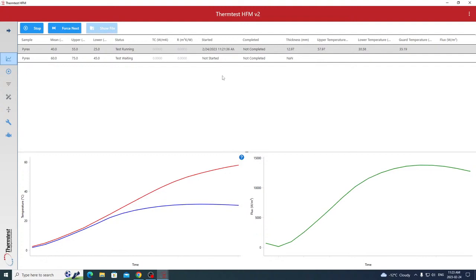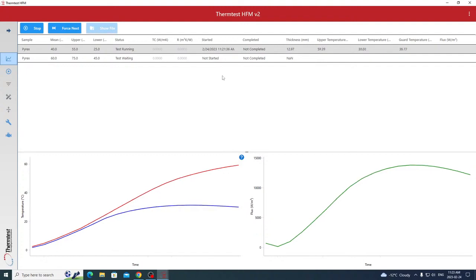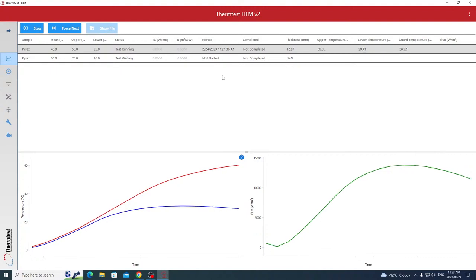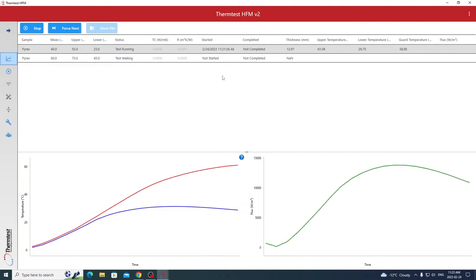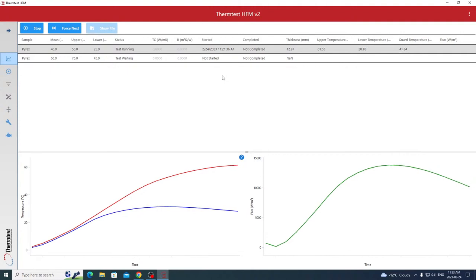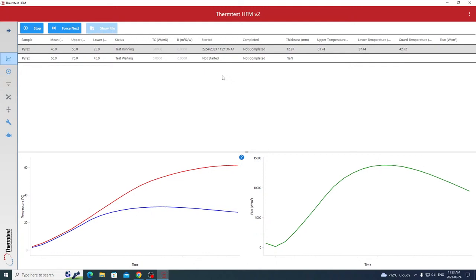Doesn't matter who the maker of the transient method is. Any heat you introduce into the sample, you have to wait for that to dissipate. So, in fact, to measure at one temperature multiple times, it takes roughly 45 minutes to an hour. Each temperature measurement on the GHFM is roughly 30 to 45 minutes. So in fact, the rapidness can be a little bit misleading, especially if you're adding in multiple repetitions.